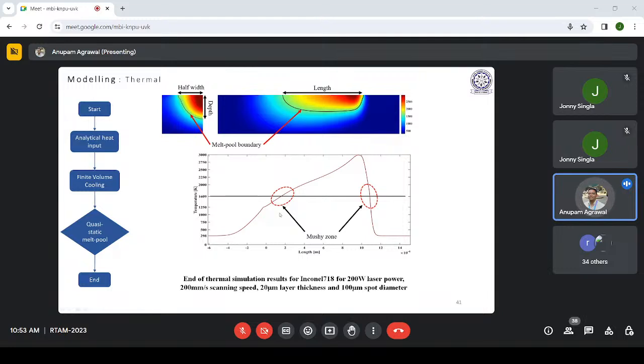So here in this figure, if we see the mushy zone, there is a temperature line 1609. So thermal simulation for Inconel 718 material with a melting point we have put as 1609. Just above that temperature, this is all in the melt pool, in the molten stage, in the fluid phase, and just below that, it is in the mushy zone, that is liquid and solid phase, both phases in a mixed solid liquid form. And then much farther from there it is all solid.